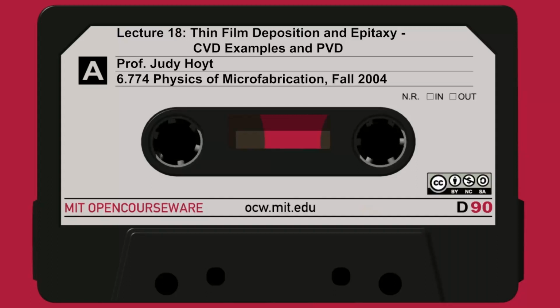The diluent gas. So what is it that you usually flow? Sometimes people flow nothing. Sometimes it's just silane flowing in the tool, relatively low. Sometimes people will use a carrier gas, such as nitrogen. Notice that hydrogen is not used typically, and there was a question, I believe, about this in the last lecture. Hydrogen is not used because it reduces the growth rate. Again, this is the reaction from silane going to solid silicon, and it involves hydrogen. If you put hydrogen into the reactor, it tends to push the reaction backwards and slow down the growth rate.